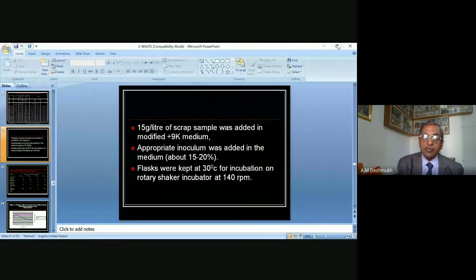Then inoculum was added. Which inoculum? As I have told you, isolated from the mine soil and from the cow dung. Cow dung was also used. And from that, a consortium was prepared, and 15 to 20% consortium was added in that. Then flasks were kept at 30 degrees centigrade for incubation on a rotary shaker. Why? Because there is a powder prepared from the electronic equipment.